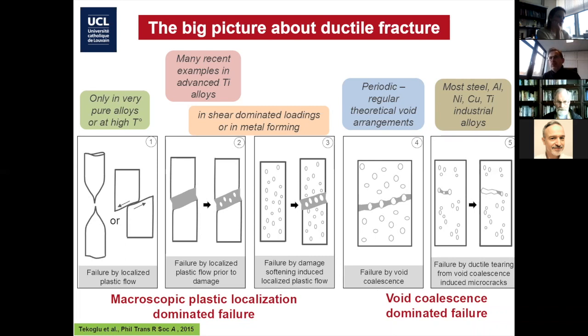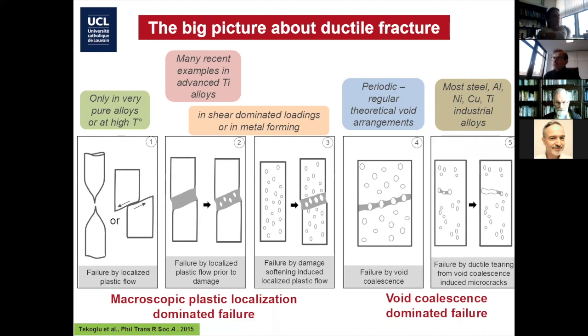Some voids will join and create a micro crack, where in other parts of the material they're still at an immature state. In between, you have a range of combinations. For instance, the number two case is where, because of low strain hardening capacity or certain types of loading conditions, you may generate plastic localization, and within the plastic localization — necking or shear band — due to large strains and perhaps the increase of triaxiality state, you will generate voids that at the end will be responsible for fracture. The opposite is also true: sometimes damage nucleates very early, and the softening induced by the voids accelerates the localization phenomenon.